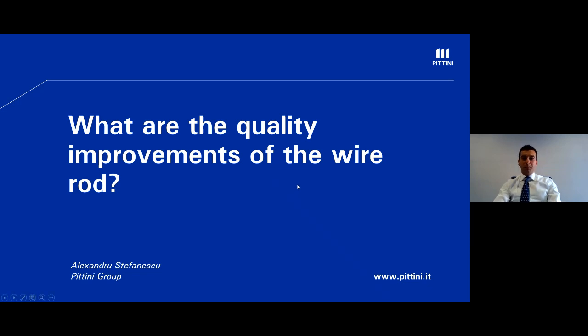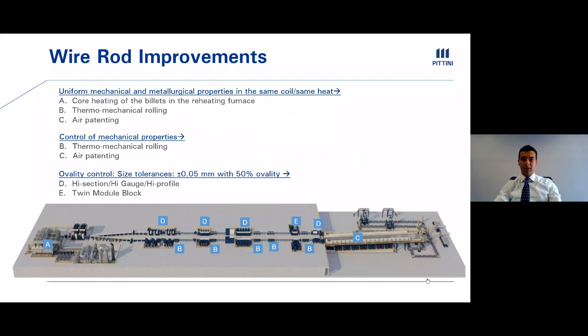Yes, Fabio, thanks. Well, there are several improvements on the wire rod produced in the new Verona rolling mill, thanks to the thermomechanical and the air patenting process. From the users' point of view, we are mainly talking about mechanical and geometrical improvement. Among others, the most important are uniform mechanical and metallurgical properties in the same coil and in the same heat. This is achieved, again among others, by the core heating of the billet in the reheating furnace, and this is guaranteed by the working beam technology. The thermomechanical rolling and air patenting are both playing a key role in achieving this result.